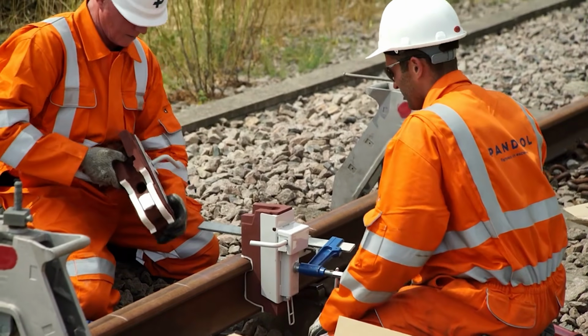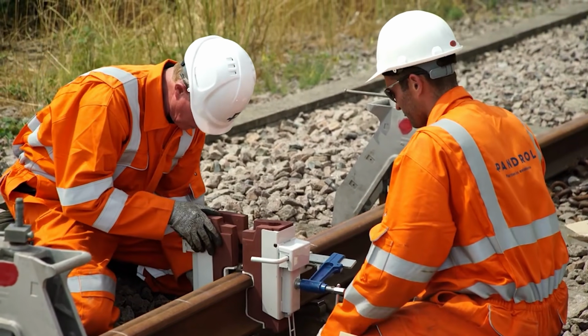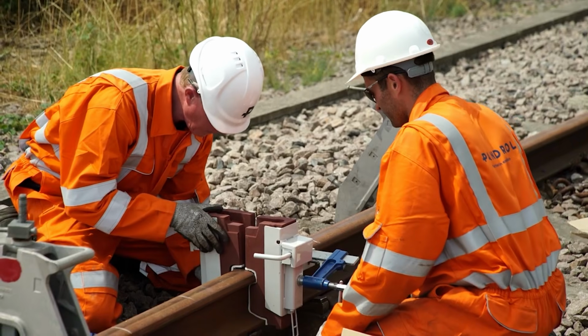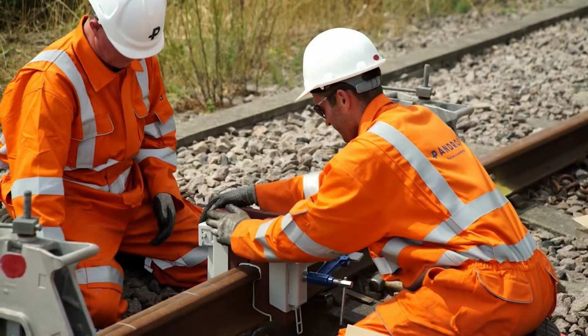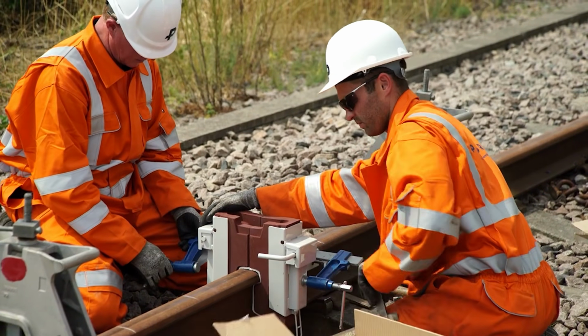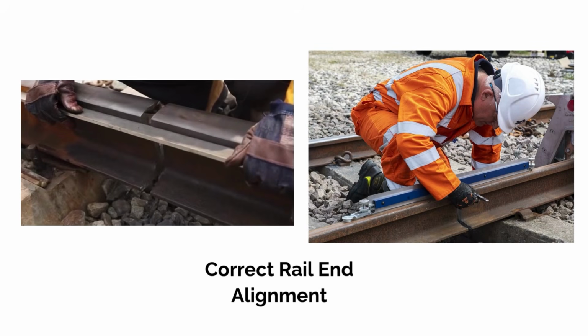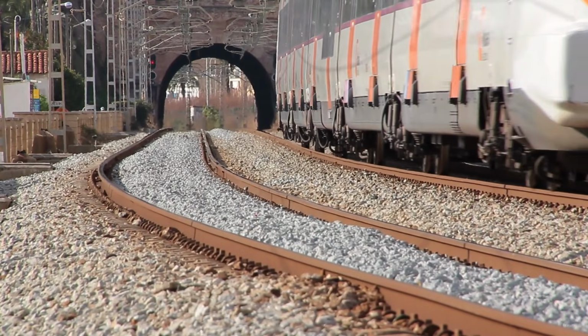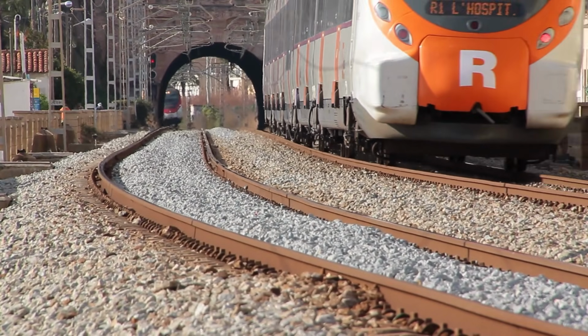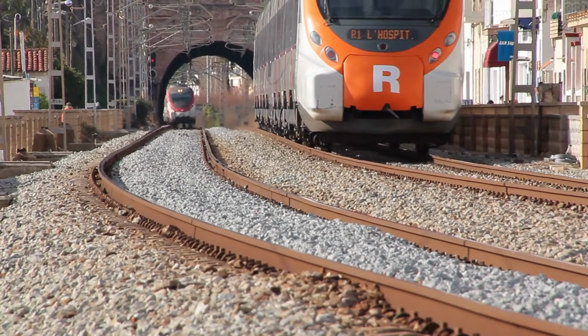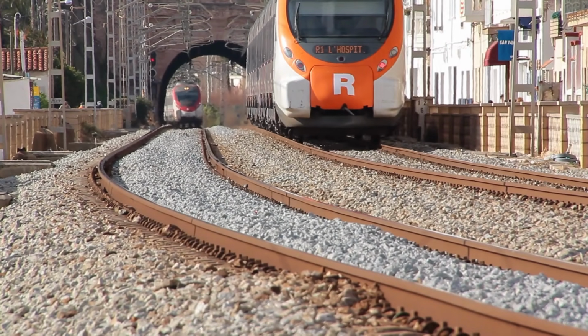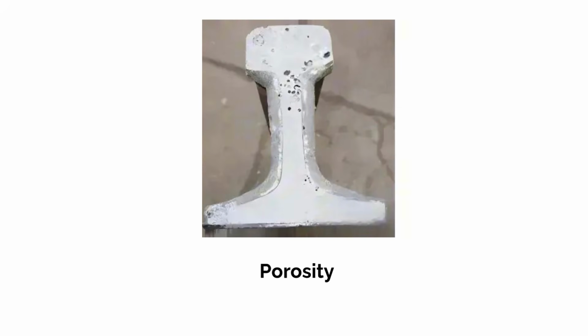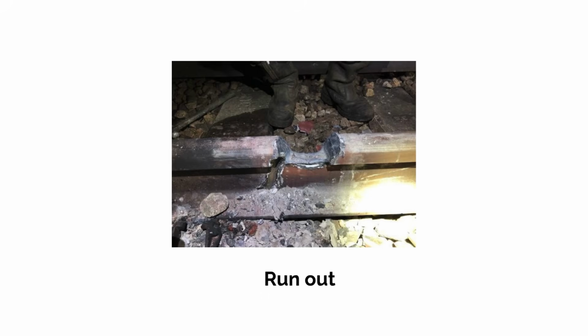Incorrect preparation, poor execution of the welding process, or issues with the rails that are joined together, or even the surrounding track itself, can all lead to failure. But what does this look like in practice? Welding requires the rail ends to be aligned properly, and the weld itself to be set up correctly. Misalignments can add stress concentrators, which put the weld itself under greater stress, leading to failure. Poor setup can lead to issues with porosity, or even the molten metal running out of the mould altogether.